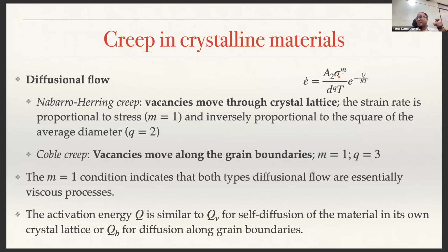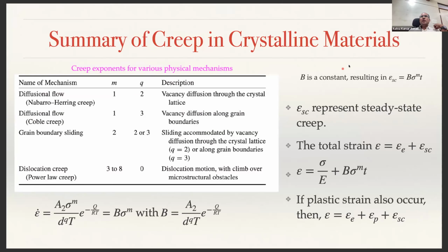Because it depends on the stress. That is why it is not necessarily proportional to stress, but stress to the power 3 or 4 or whatever. So in summary, depending upon the mechanism, if it is diffusional creep, M is equal to 1, Q equal to 2. Coble creep, M equal to 1, Q equal to 3. In grain boundary sliding, it is 2 and 3. If it is dislocation creep, Q will not be playing any role, but M will have a large range of values, 3 to 8. Okay.